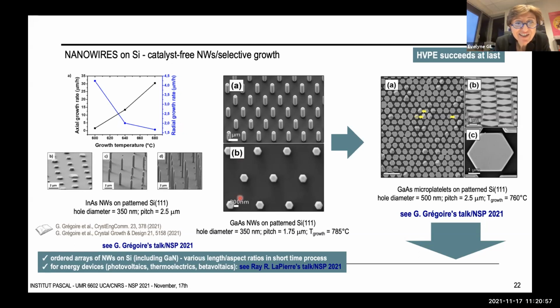You will have to ask Grégoire this afternoon to know exactly all the pitches that are used. But yes, we had several pitches on the micrometer scale, and I don't remember if you had some substrates available with smaller pitch, but the pitch is not an issue in HVPE because there is no adsorption of the growth precursors on the dielectric mask, so we are not submitted to any diffusion between. It's perfect selectivity. So yes, it's perfect selective growth due to the growth anisotropy of crystals.